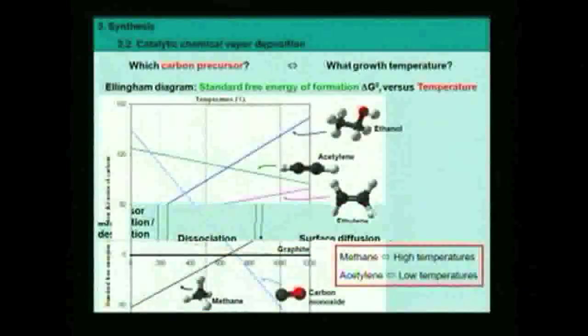Okay, now we are going to discuss how to choose the best catalyst and the best carbon precursor. This is a general approach that can be used for other chemical reactions. When you want to grow something, which reactant are you going to use? Which catalyst are you going to pick? Here, we want to make graphitic structures like graphene and carbon nanotubes. Basically, their formation energy is similar to graphite. It's about the same. The formation energy of graphite, by definition, is 0.